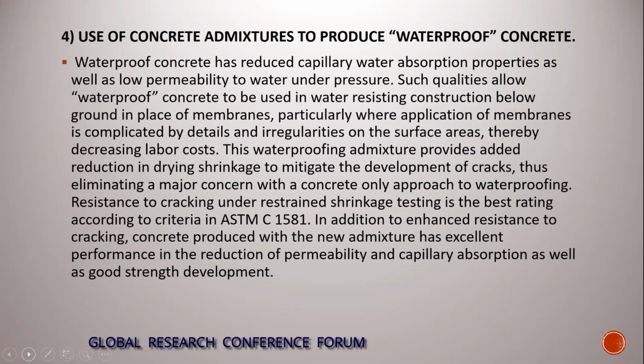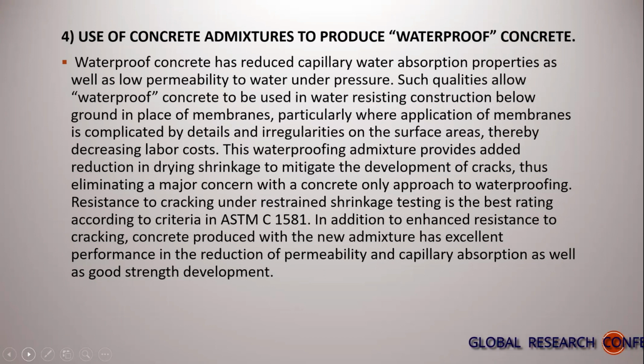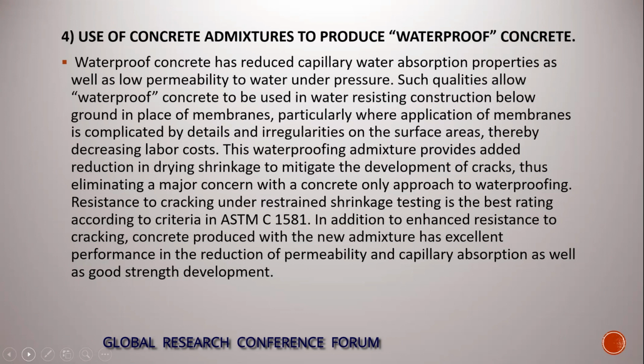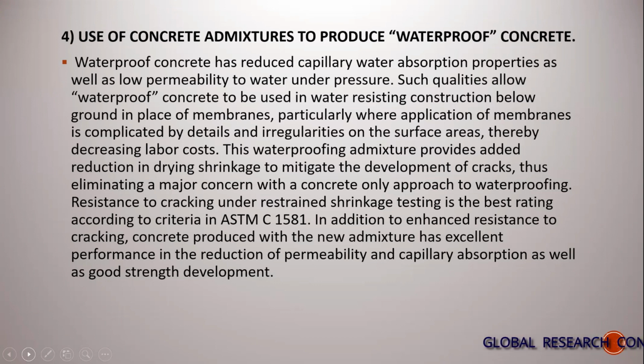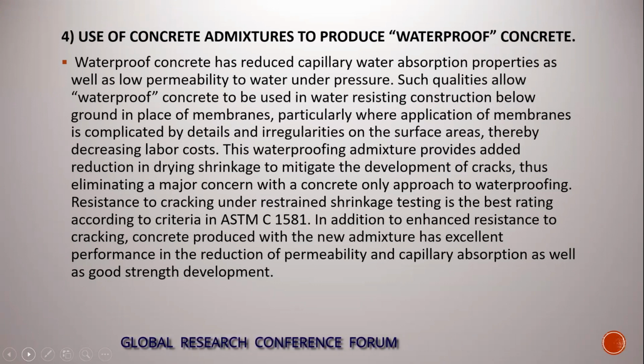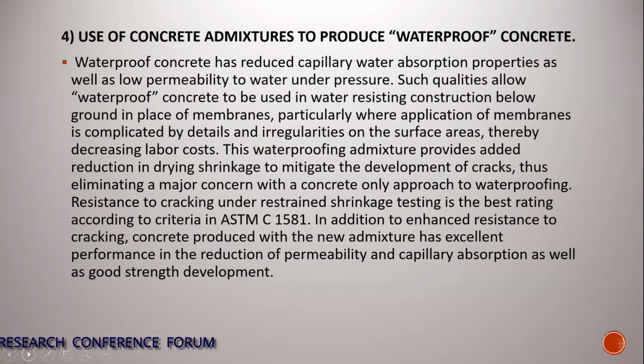Resistance to cracking under restrained shrinkage test is in the best rating according to the criteria in ASTM C1581. In addition to enhanced resistance to cracking, concrete produced with the new admixture has excellent performance in the reduction of permeability and capillary absorption, as well as good strength development.